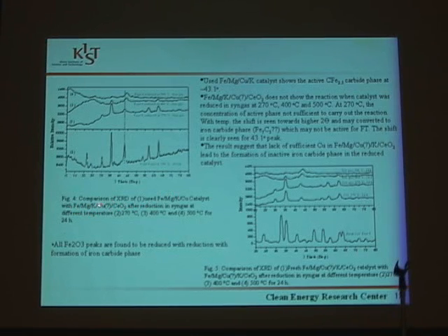FeMg potassium Cu. Actually, I have written a question mark here because copper we had taken during the precipitation of the catalyst, but we don't know whether it is there or not because the results have shown that copper was not present, or may not be at the particular level which we desired. So that is why this XRD shows that this is a catalyst which was reduced in syngas at 270, 400 and 500. So this iron carbide phase, it can be clearly seen that it is shifted from this particular peak.